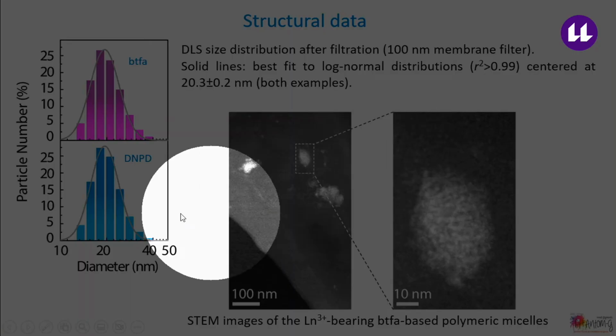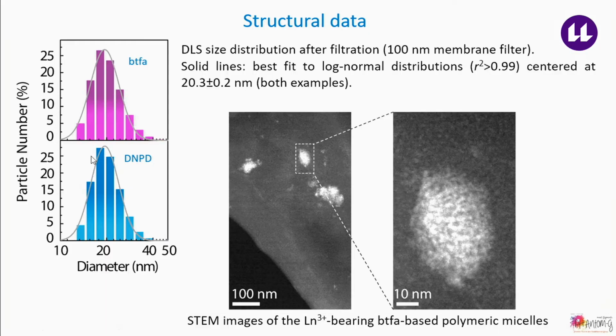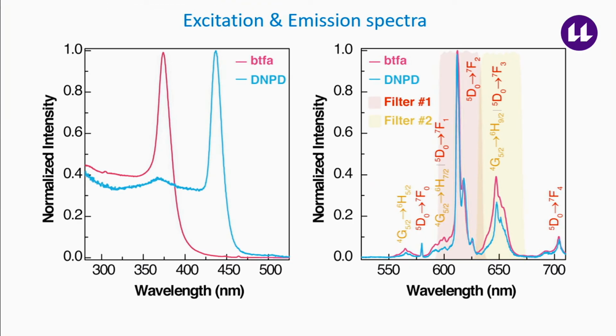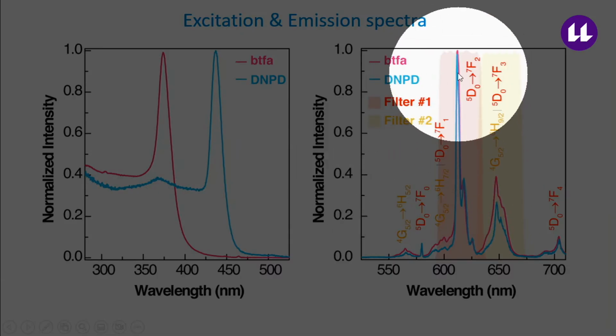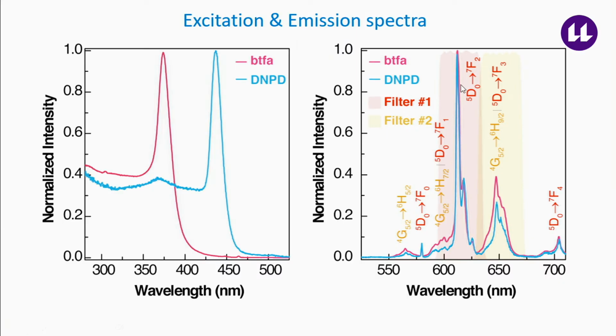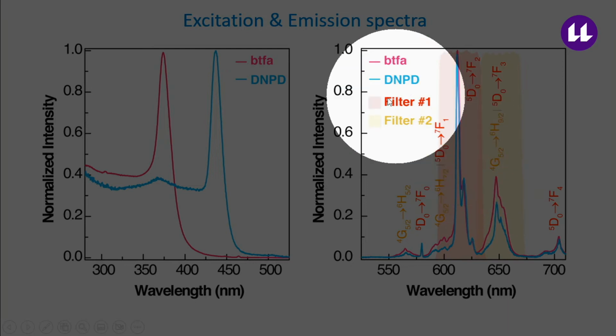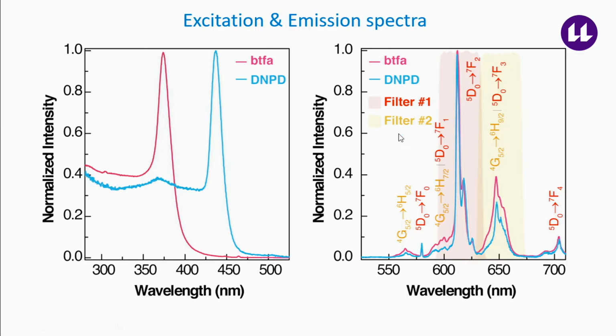These are some structural data showing that we are, in fact, working with micelles of an average size around 20 nanometers. And these are the excitation and emission spectra. I call attention that we will use emission from europium that lies in a region that is superimposed to one filter. I will explain this better later. And the samarium emission was superimposed to a spectral region which is coincident to a second filter.